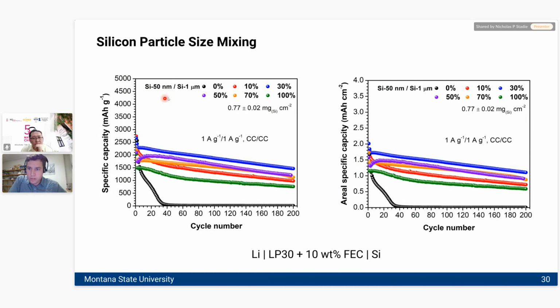The 50 nanometer precursor was probably one of the smaller nanoparticles that we had of silicon. It wasn't a great material on its own, and it was pretty hard to handle. So we didn't really like working with it. It was very fluffy. But what he did was he made mixtures of it. So here we have 0%, 10, 30, 50, 70, and 100% mixtures between a 50 nanometer and a 1 micron particle silicon. And you can see here what happens when you have no nano. So this is the 1 micron particle.